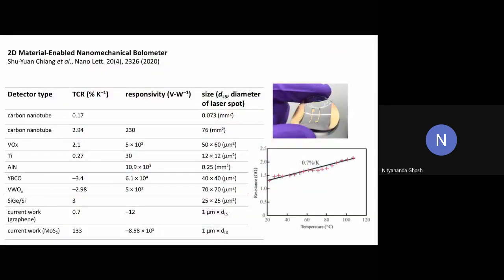Besides this, people are nowadays also trying to make these kinds of bolometers using a wide variety of 2D materials that people synthesize in the lab, including graphene, reduced graphene oxide, or molybdenum sulfide. The following work by Chiang et al. came up recently, and they had come up with a responsivity as high as 8.58 times 10 to the power 5. This is one of the record responsivities for bolometers. So this is expected to open floodgates for looking at 2D materials for bolometry applications.